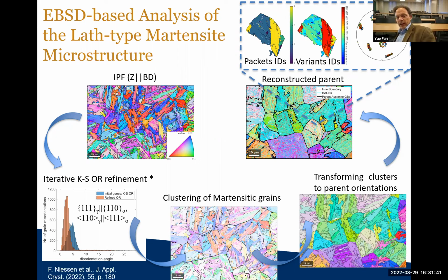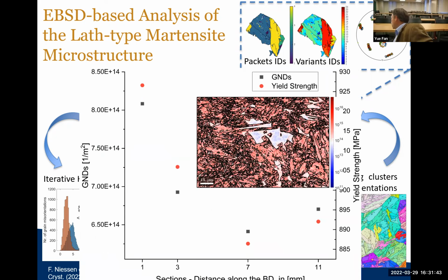And what you can also get out of this are the geometrically necessary dislocations in these microstructures. What we see is there's a delta ferrite grain or phase here in the martensitic phase, and all the red in here is the highlighted dislocations. Now, what you plot is the dislocation density as a function of distance along the build direction, but also the tested yield stress. And of course, if you have a higher dislocation density, you get a little bit higher yield stress.